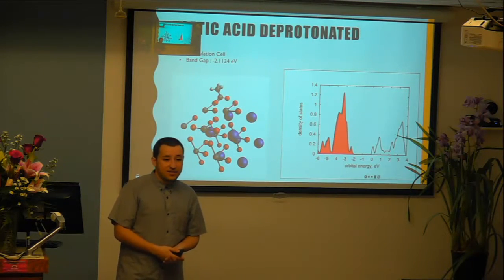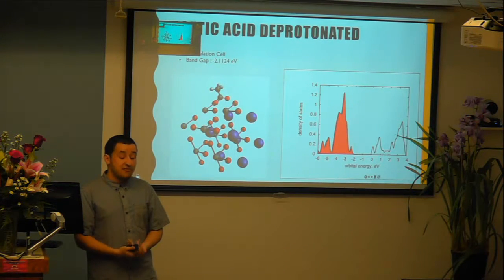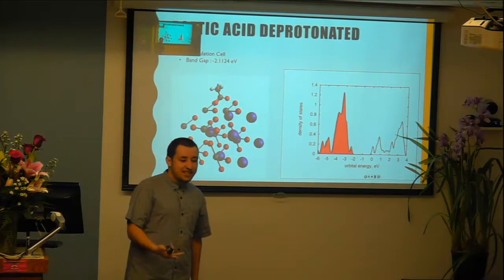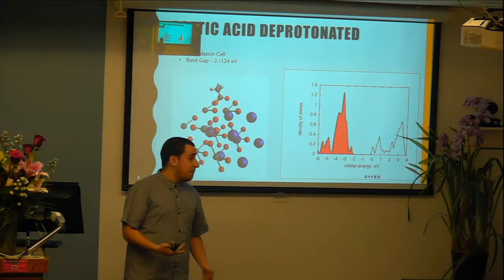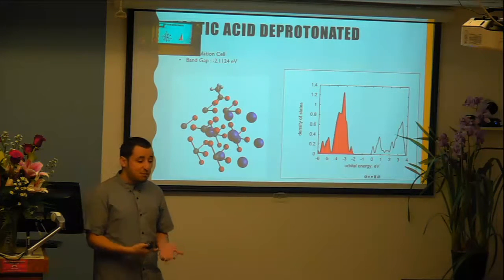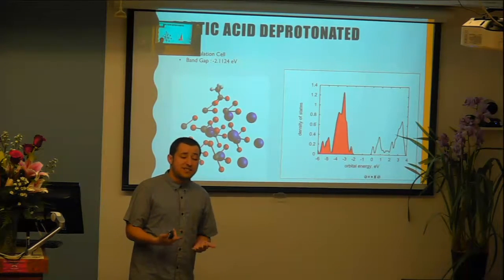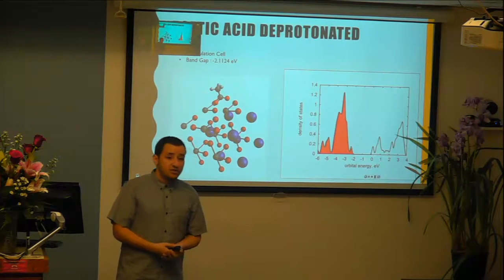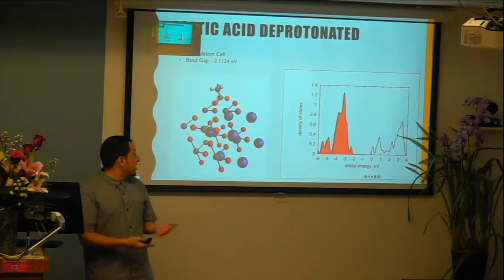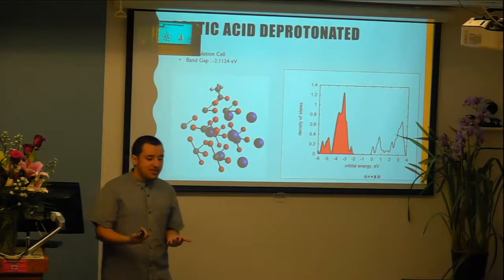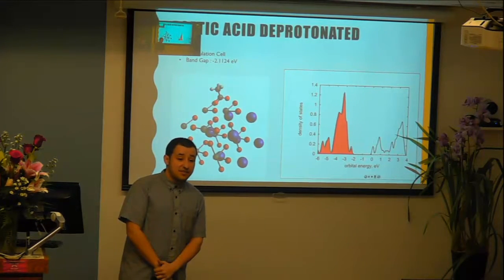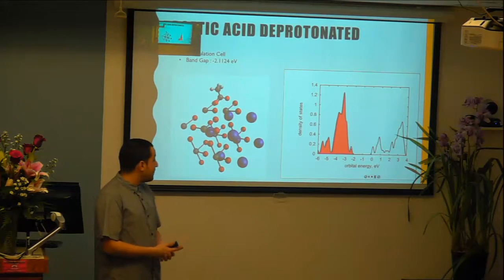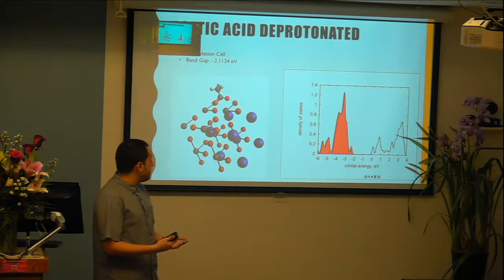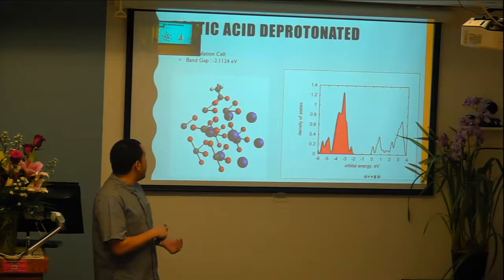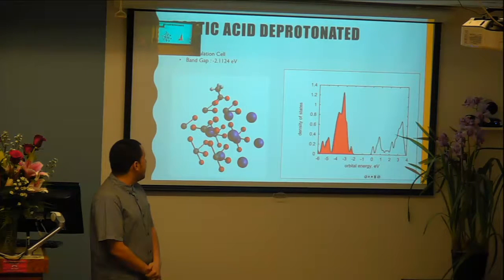I mean a p-type semiconductor, which means it can be readily oxidized, and it makes this a ligand that can pretty much determine itself as an electron hole carrier. So in this type of structure, this is what we call a p-type semiconductor, and this ligand would be perfect for that. And whenever I ran this cell, I found a band gap of about -2 eV, or electron volts.